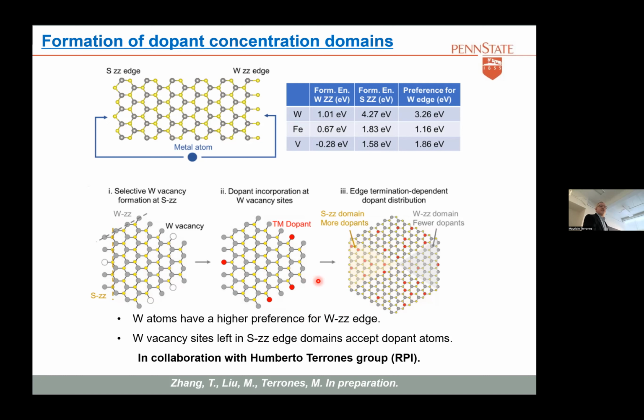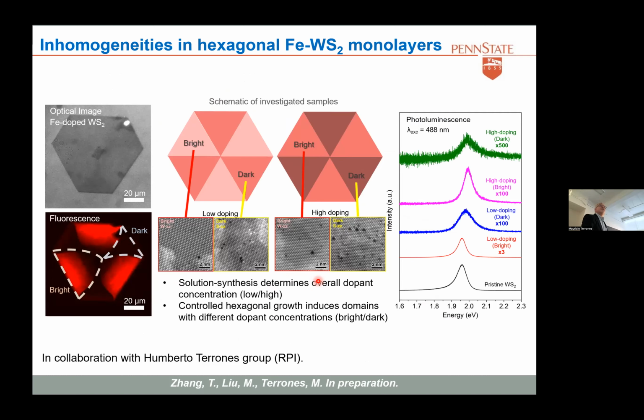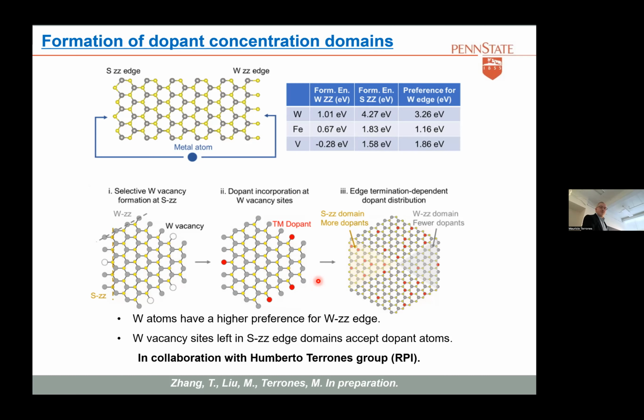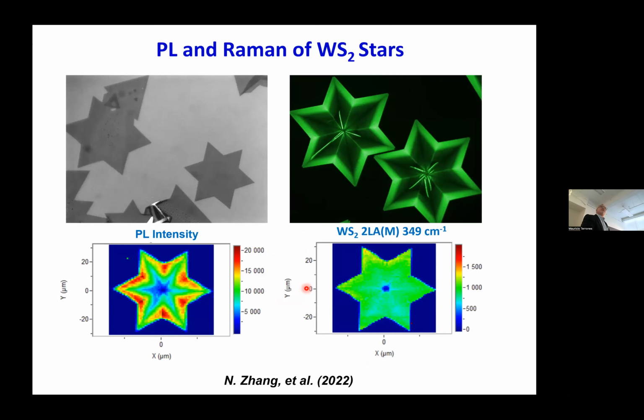But I think the nice thing here, and we have seen it with other systems, is that with chromium as well, the dopants tend to go to the sulfur terminated edges. So you can control where you want your dopants in that case. And again, here, in order to get the hexagonal shape, we played a little bit with the sulfur concentration. We played with less sulfur concentration, so we could have the hexagonal lattices. Again, we're working on this, and in principle, if you control the dopant, the sulfur concentration, where the dopant is going, and temperatures, you could in principle get this beautiful structure as well. These are made of tungsten disulfide.